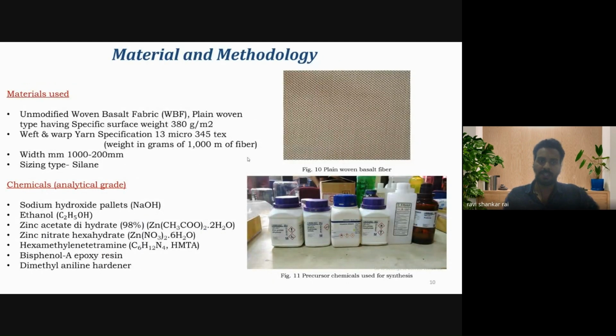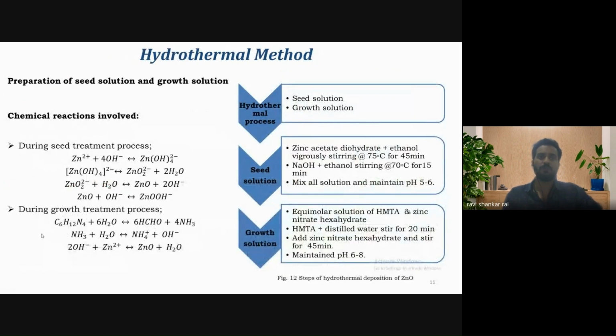Why? Because zinc oxide has another very good property, which is large growth directions and large morphological characteristics. For the synthesis of the nanostructure, we have used different materials, which is woven basalt fiber, with different specifications mentioned here, and a set of chemicals of analytical grade. Zinc acetate dihydrate, zinc nitrate hexahydrate, hexamethylenetetramine, and a dimethylaniline hardener have been used. In the hydrothermal method, we need to prepare two types of solution, which is seed solution and growth solution. People usually make only growth solution, but this is a fabric-based growth, so that's why we have added the seeding solution, which will be discussed in the further slides.